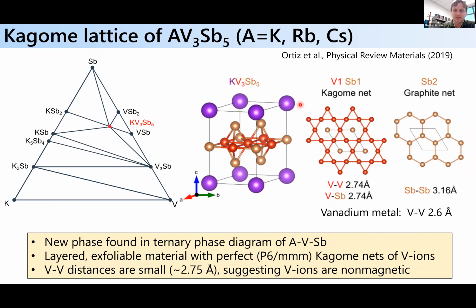And so here I've shown you the crystal structure for potassium, vanadium, 3 antimony 5. Basically, you have a perfect kagome net of vanadium ions, which is coordinated by antimony. And in between these layers, these V3Sb5 blocks, you have a layer of alkali metal ions. Okay, so then you can decompose this into different sublattices. One is an antimony 1 sublattice, which is in the kagome plane of the vanadium ions, and the other is these graphitic nets of antimony above and below this plane.